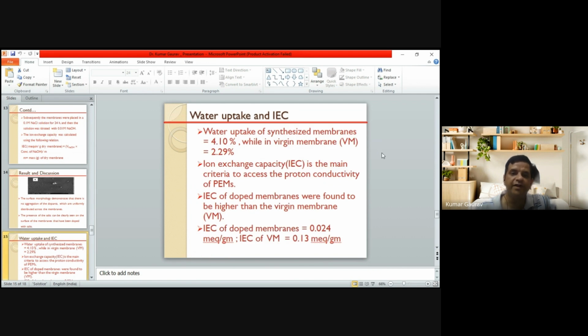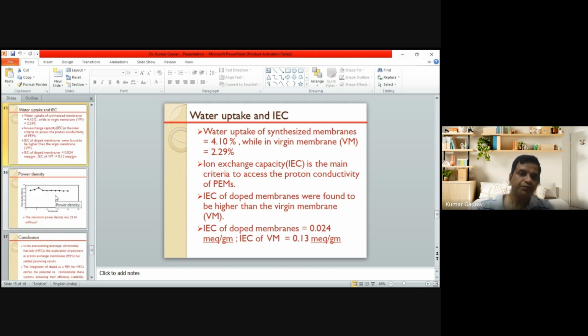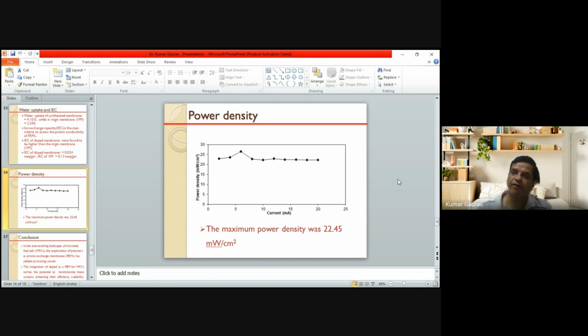After that, we compared the virgin membrane and the synthesized membrane. For the synthesized membrane, the water uptake is around 4.1%, but in the case of the virgin membrane there is no addition of the dopant. After that, we calculated the ion exchange capacity, which relates to the proton conductivity of the membrane. The ion exchange capacity of the doped membrane is 0.024, and the virgin membrane is 0.13 equivalent. And we calculated the power density of the synthesized membrane. The power density was 22.4 milliwatt per centimeter square.